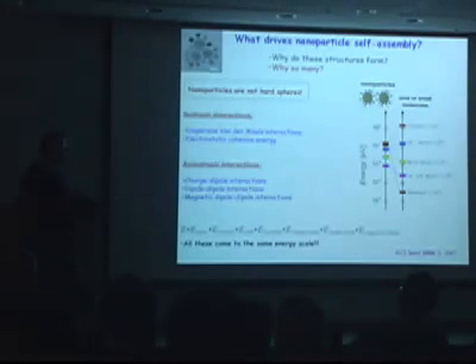And it turned out that for objects in the size range from a few nanometers up to a few tens of nanometers, all these interactions squeeze into the same order of magnitude. I don't know if there is any deep physics behind it, or it's just a coincidence for these particular particles. But from a practical point of view, we have multiple interactions. Each of them has a different scaling law, and they all contribute with comparable weights to the interparticle potential.